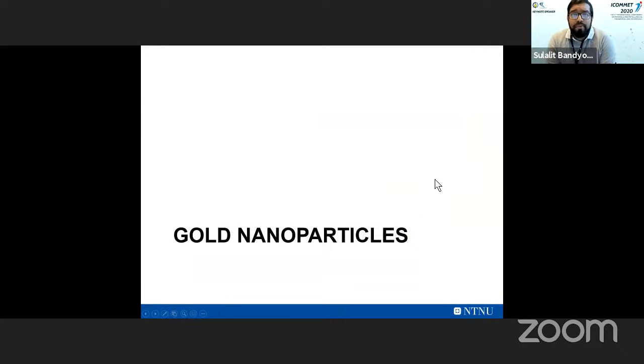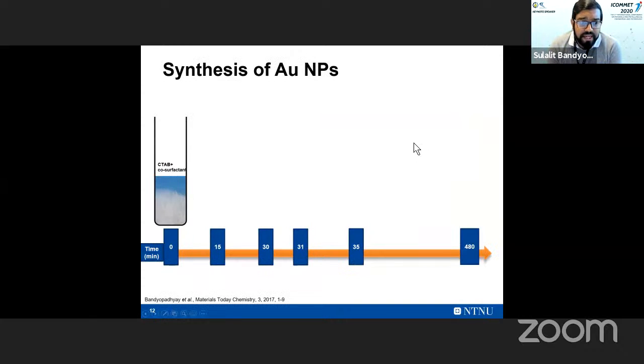With that, I will take you to the tailoring that we do in our labs, meaning that I'm going to show you now how we do this and what we gain out of these processes. So first and foremost, with the gold nanoparticles, what we have done so far is that we synthesize these gold nanoparticles using a seeded growth technique, which means that we add some gold seeds, and then by controlling the reaction parameters, we change their size distribution, shape, morphology, and so on.